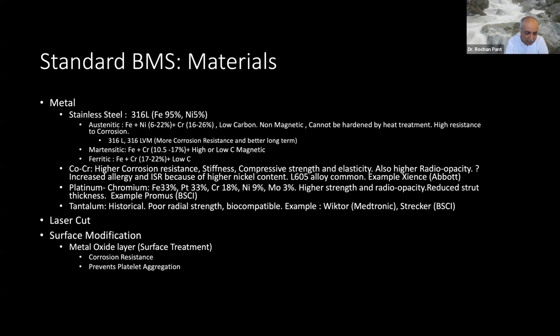Cobalt chromium is a little more expensive, has become more popular because of corrosion resistance and more stiffness, so you can make thinner struts. But some people claim it gives rise to higher in-stent restenosis. Data is not completely clear on this, but a very popular coronary stent, Xience, is the cobalt chromium stent. A lot of renal stents are cobalt chromium, and a lot more balloon expandable stents are becoming cobalt chromium as compared to 316L steel. Platinum chromium is even more radio opaque, higher strength, but of course it is more expensive, platinum being a more expensive metal, and so that is in use in some stents, mainly in the coronary world.